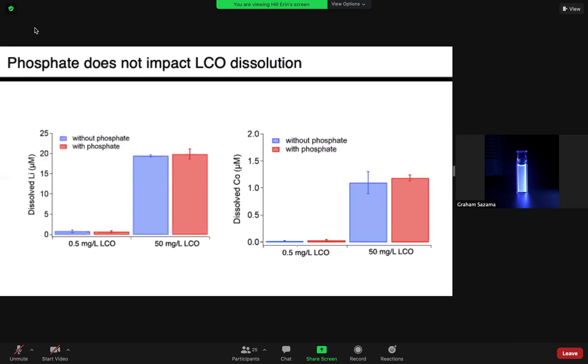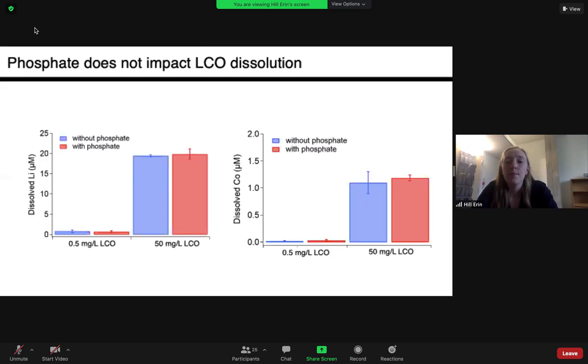The release of lithium and cobalt was analyzed using mass spectroscopy, specifically inductively coupled plasma mass spectrometry. ICP-MS allows us to detect most elements at a very low level. The sample gets nebulized, which creates an aerosol, and the aerosol is introduced to a high-temperature plasma, which atomizes and ionizes the sample. A mass analyzer separates those ions based on their mass-charge ratio, and the ions get measured by a detector.